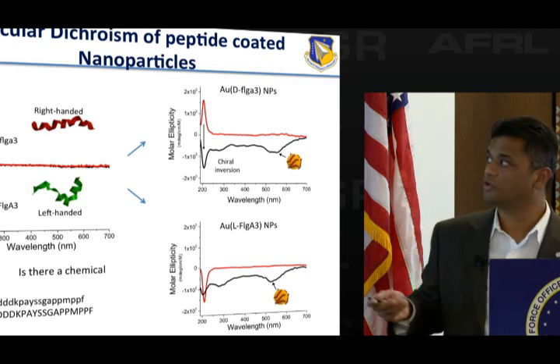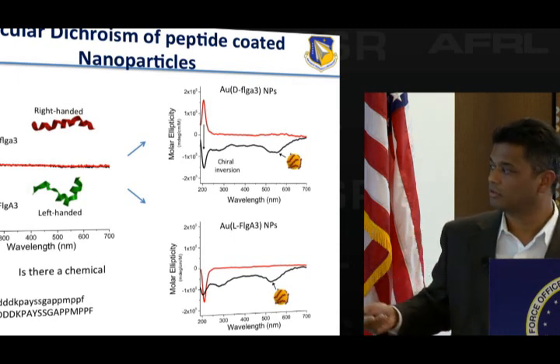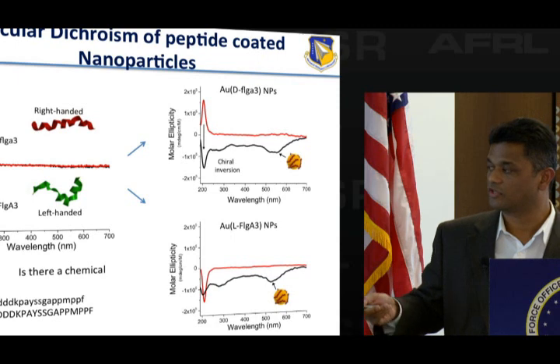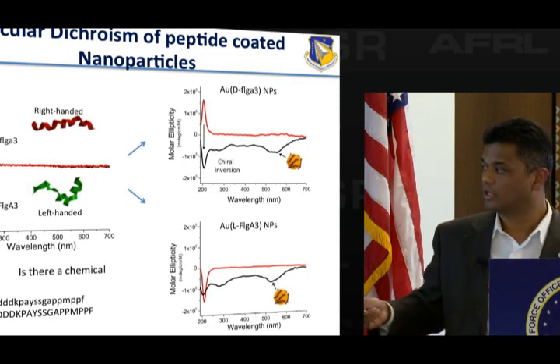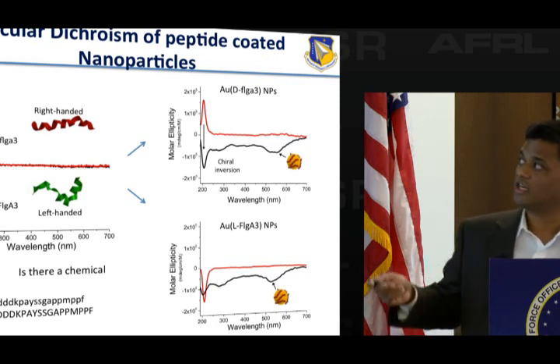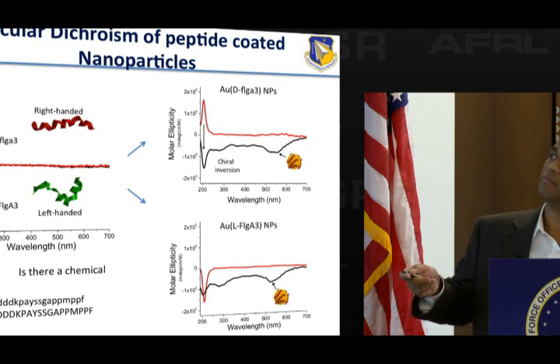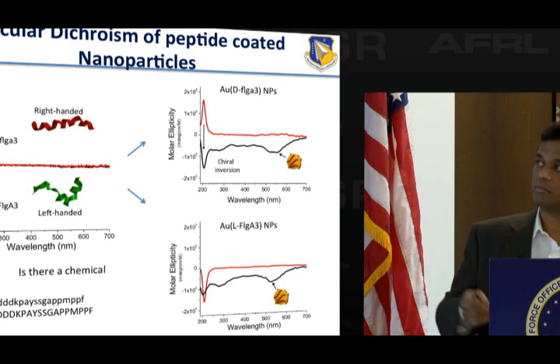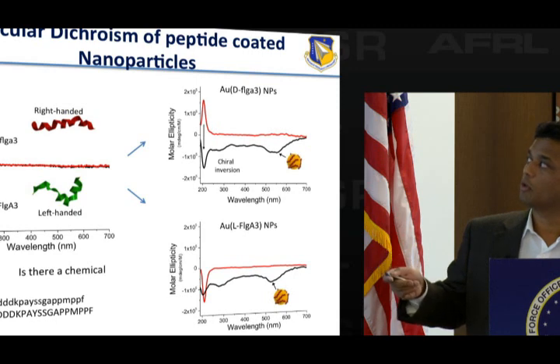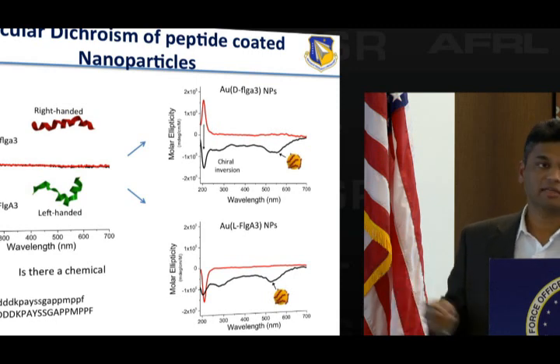Because what I showed you earlier is that when I put that gold nanoparticle, I get the negative peak, which corresponds to the negative peak of the peptide. So both of them are negative. But what I saw is when I took a right-handed peptide, which has a positive peak, as I mentioned, because it's right-handed, and I mixed it with my gold particle, I get a chiral inversion of the peptide.